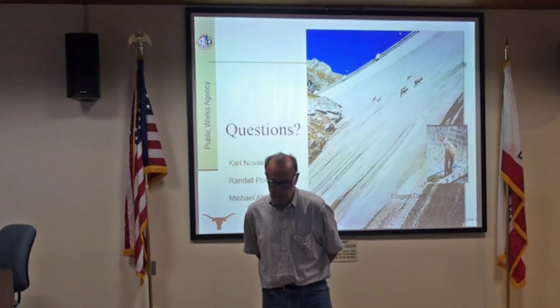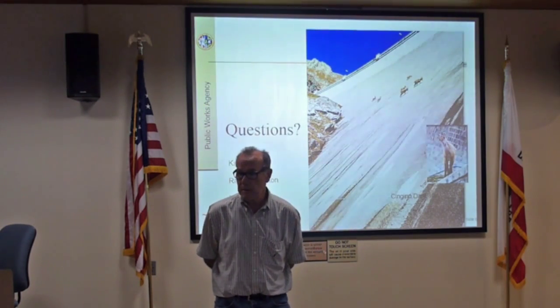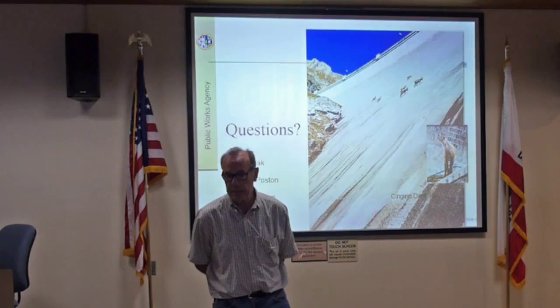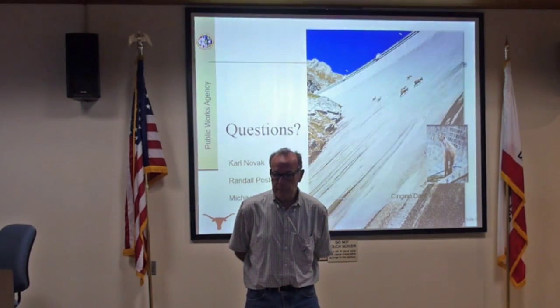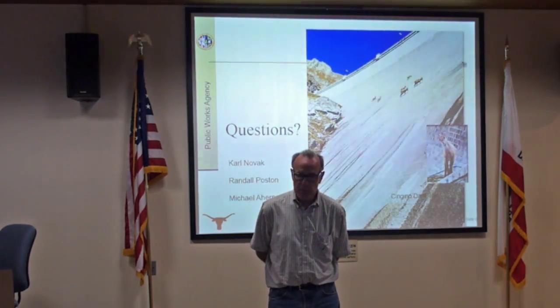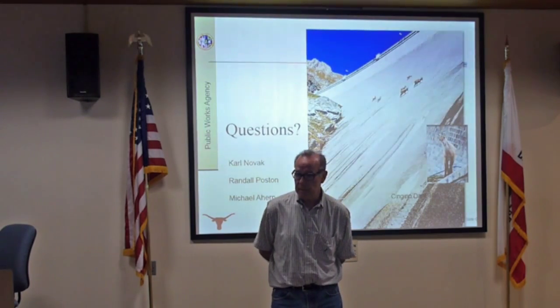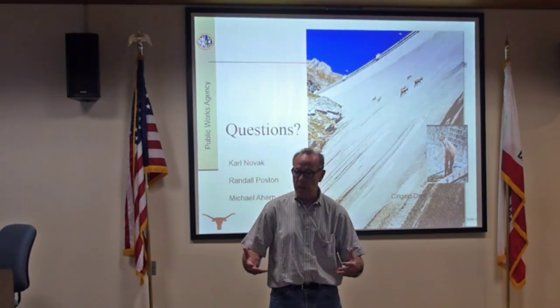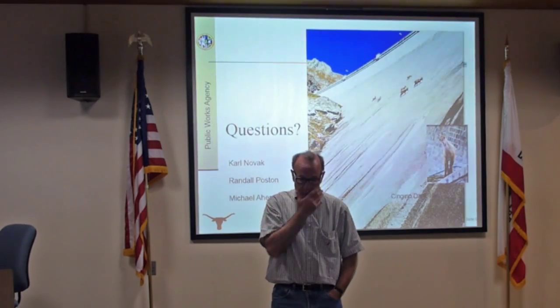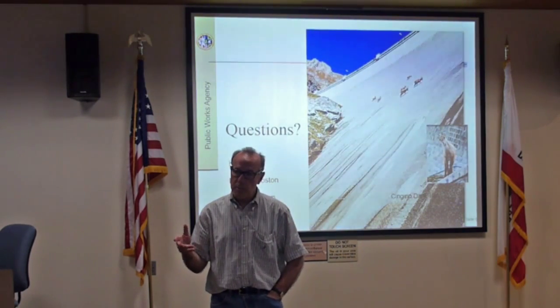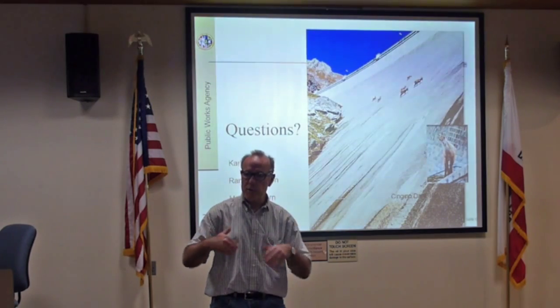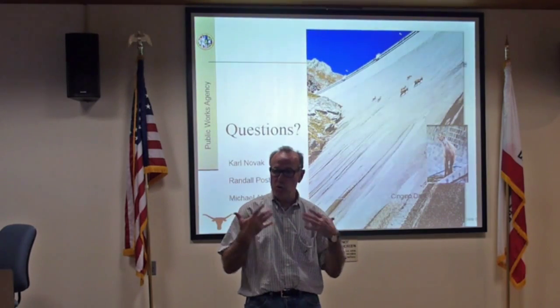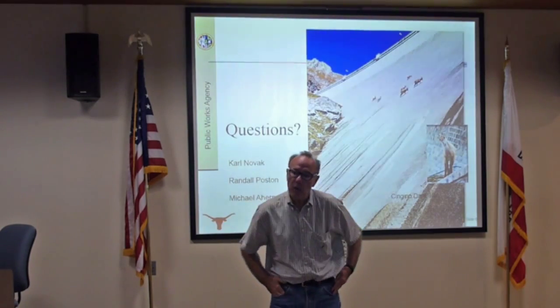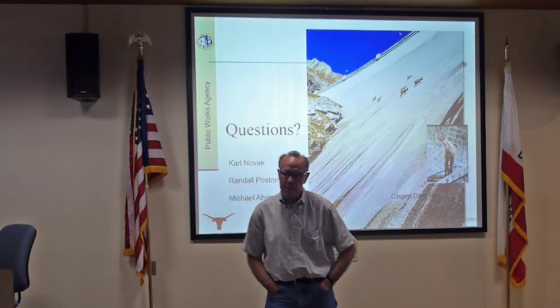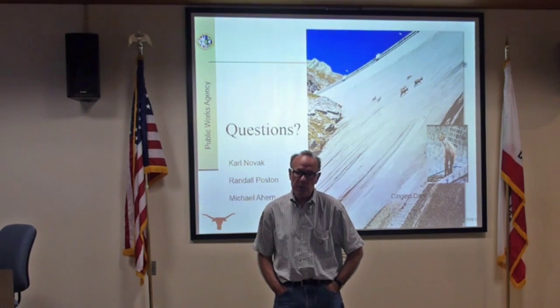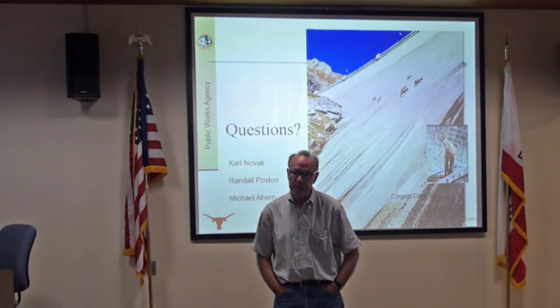Yeah, well, there are some that aren't, nothing's commercially available that I'm aware of. The one that people have used, and I'm not sure I can describe all the chemistry myself, is lithium, a lithium-based product that they admix into the concrete. If it's admixed, it's shown to work pretty well. They've tried to do that as a retrofit process where you go out and inject a lithium base. That hasn't worked that well, but as an admixture, lithium seems to have some promise. I'm not aware of any commercially available product though that does that.